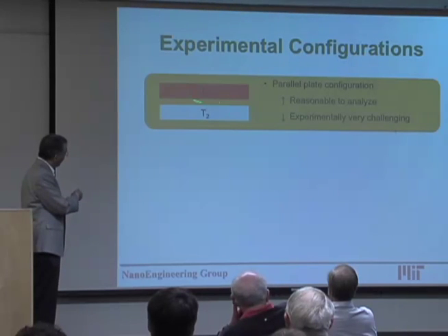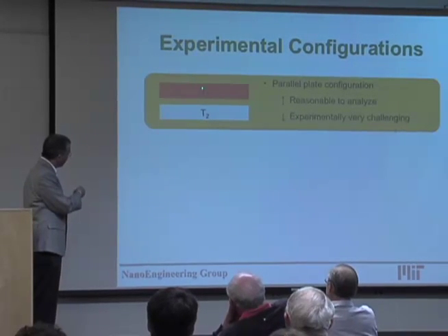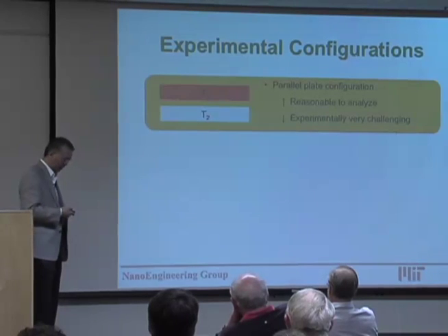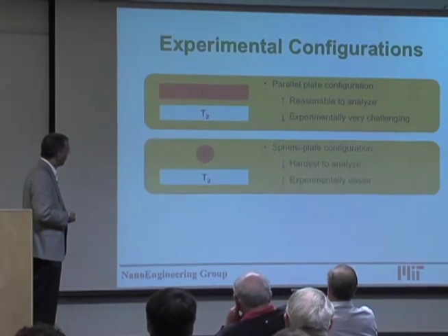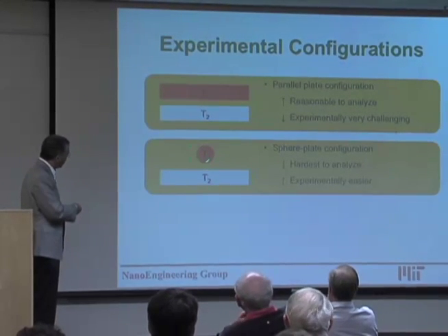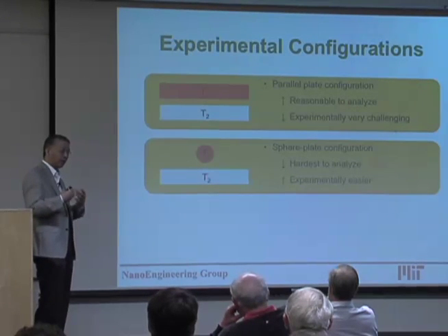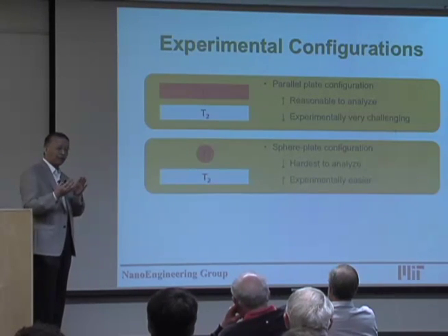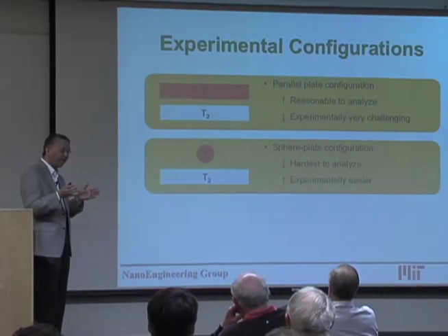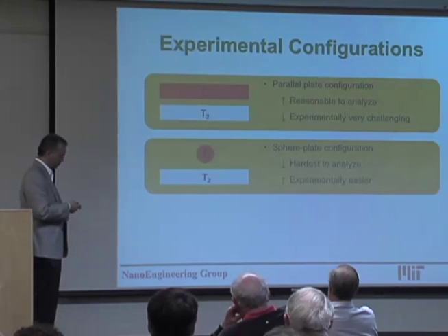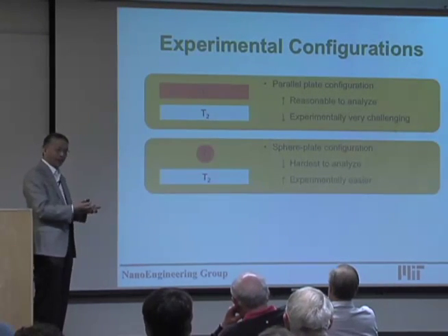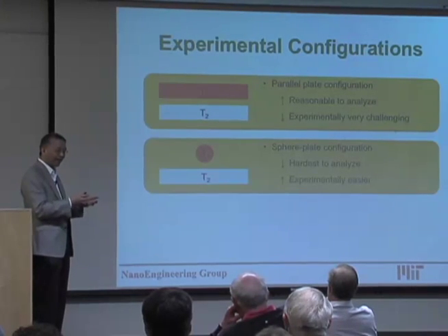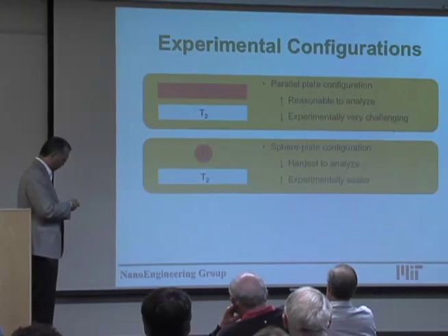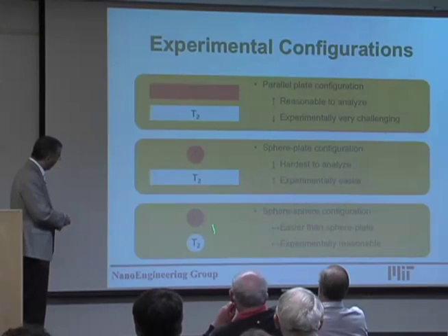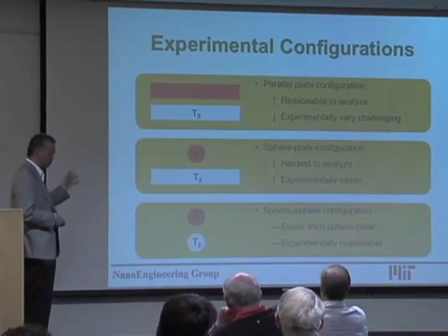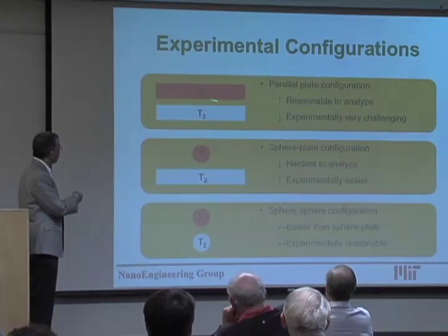One can start with the simplest, which is the parallel plates, because the theory is well established for parallel plates, or a sphere and a plate. For the parallel plate, the difficulty is maintaining two surfaces parallel down to the nanometer regime. If you have a sphere, experimentally it's always aligned, and that's an easier experiment to do, and also the calculation. So we considered all this. We started with two parallel plates.